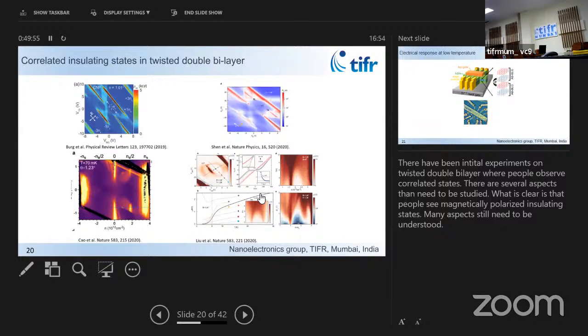What happens is that physics of correlation arises because you have these flat bands, which I sketched earlier. You have these bands, flat bands. This is energy. Then when it's exactly half filled, this band is exactly half filled, the interaction between the electrons spontaneously results in a gap, which is, I would say, a correlated gap, and that happens because these systems have flat bands. So they are behaving like some other complex material that people have been studying for many years. But here it's all carbon. Only thing is you have exquisite control over the bandwidth relative to the interaction energy scale.